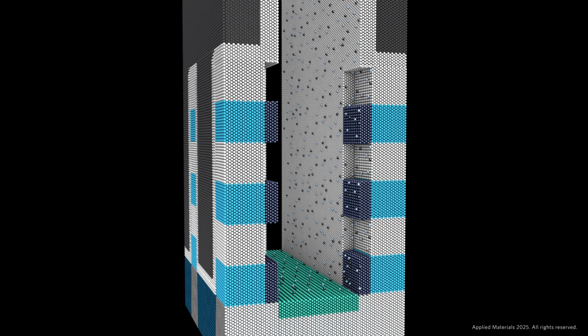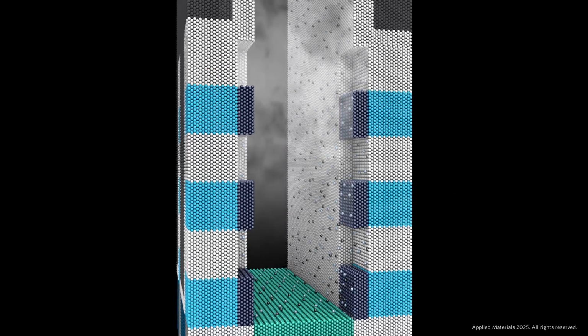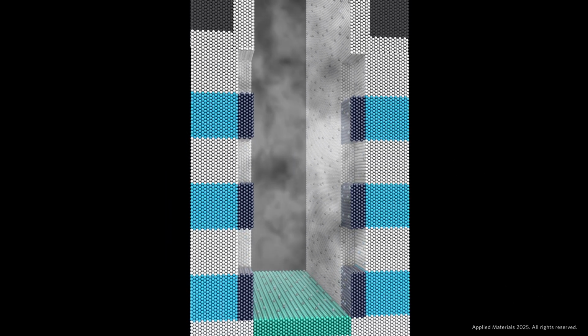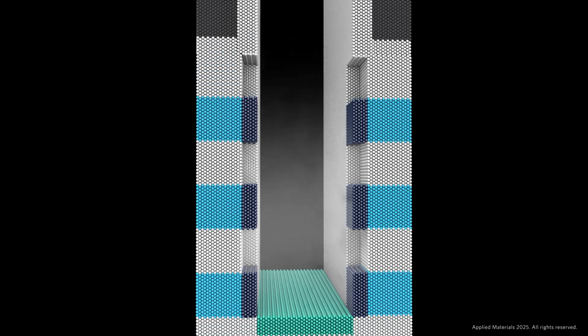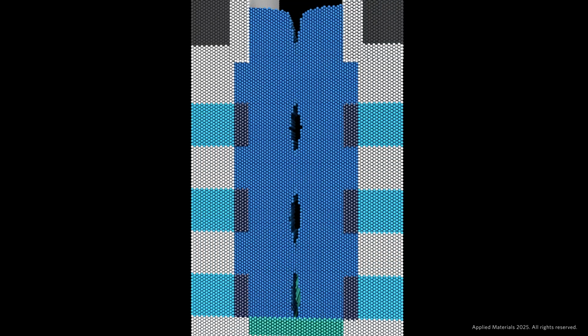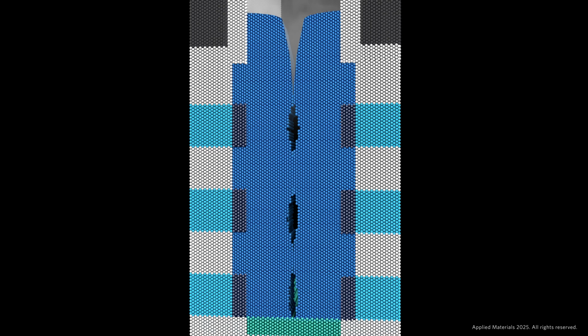The process of filling source and drain cavities begins with a selective high aspect ratio cleaning step that prepares growth surfaces while also protecting multiple materials. Finally, highly doped crystalline silicon is grown through selective epitaxy using a cyclic deposition etch process that continuously optimizes the trench opening as material grows on the sidewalls and bottom of the trench.